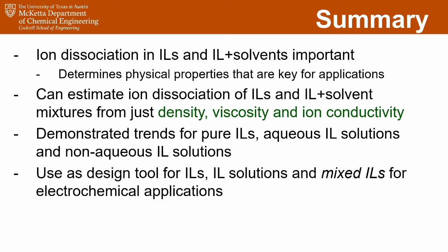I think the benefit of what we've shown here is that you can get pretty decent estimates of the ion dissociation of ionic liquids and ionic liquid solvent mixtures just by using density, viscosity, and ionic conductivity measurements, which are much easier and much faster than the NMR measurements.